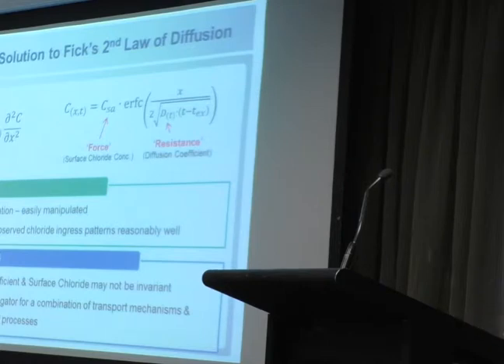And typically, people use this in two different ways. They use it for experiments in the laboratory, where they've taken great care to try and measure a true diffusion coefficient on saturated concrete, where ingress is only a result of chemical gradients in fully saturated pores. But they also go out and just use it to characterize chloride profiles in structures where you've got multiple transport mechanisms at work, as you've already heard. So possibly capillary absorption, wicking, permeation, as well as true diffusion through partially saturated concrete pores.